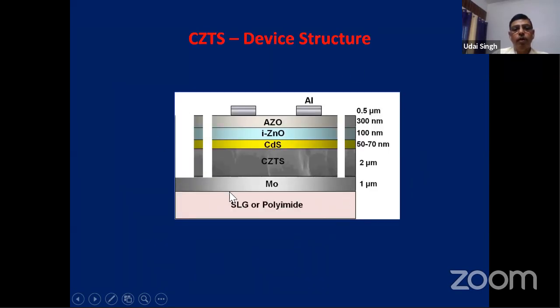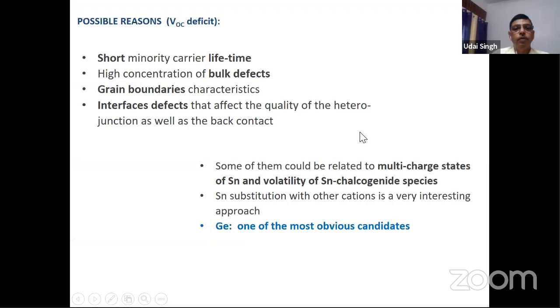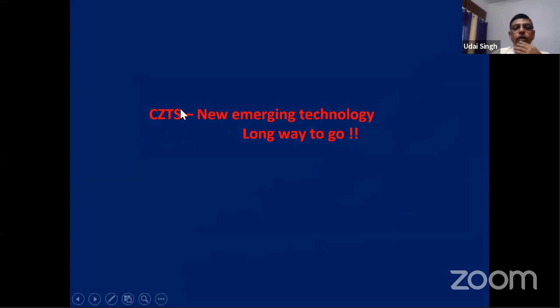Structure wise also the same. You have the soda lime glass or the polyimide substrate, then molybdenum deposited as a back contact, then the absorber layer of copper zinc tin sulfide or selenide, then cadmium sulfide to make a PN junction, then intrinsic zinc oxide and aluminum doped zinc oxide. So structure wise again the same, but the only problem is that they have a large number of secondary phases and defect states, which kill the efficiency. I will just skip this; people have tried to replace some with germanium. Okay, so CZTS is basically a new emerging technology, but still a long way to go.